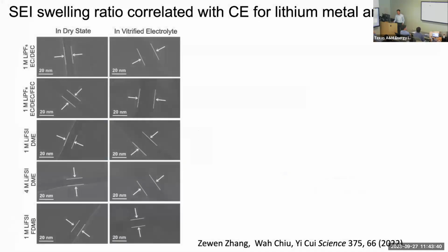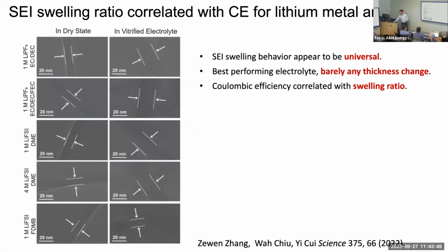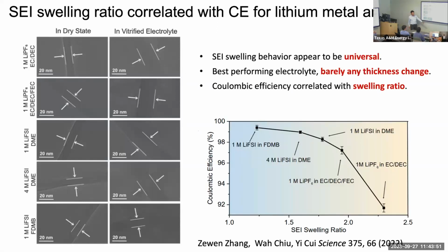But then we compared different electrolyte recipes. These are all different solvent molecules right there. Now plotting this, the SEI swelling ratio is the wet state thickness divided by the dry state. And the vertical axis is an electrochemical parameter called Coulombic efficiency. The higher the better. Coulombic efficiency describes, if I store 100 electrons during charging, how many can I get out? You want it to be 99.99%. Even losing 1% is not acceptable, right?